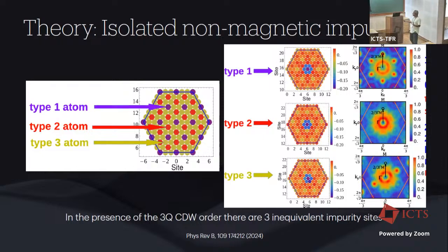Now, the interesting bit is, if you were to now ask the question, is there then inherent 2-foldedness in the presence of non-magnetic impurity? Probably not true for global measurements, because there would be 3 equivalent 60-degree rotated structures of this type of 2-foldedness. So if you are doing a global measurement of magnetoresistance, they will average out. What is interesting is, if you were to put an in-plane magnetic field in your system, there is a spin-orbit coupling. Can those 3 equivalent 2-folded regions become inequivalent or not? That is also a quantitative question, not just qualitatively.